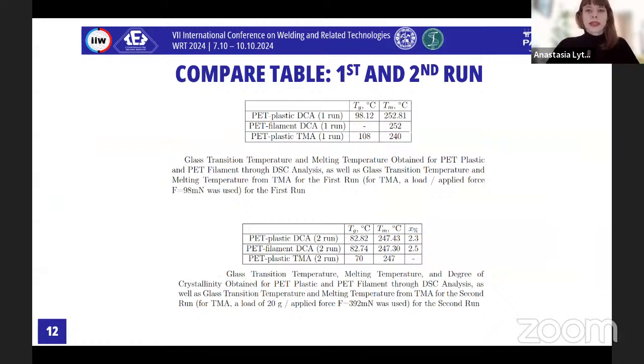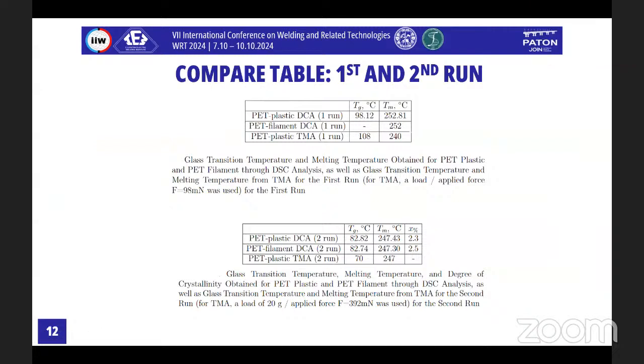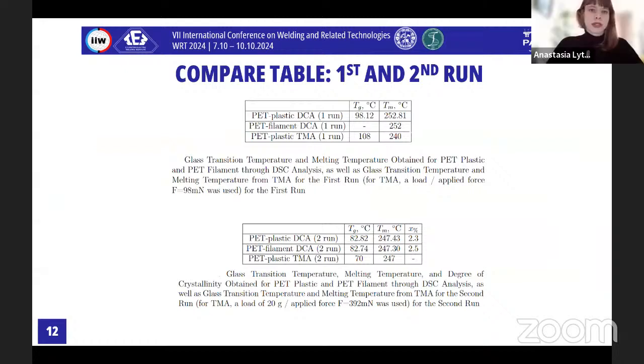So when reheating the filament occurs, the material does not change its properties during the heating run, so we can reheat it multiple times. And the melting temperature for PET plastic determined by both analysis methods also shows only a minor difference within tenths of a degree.